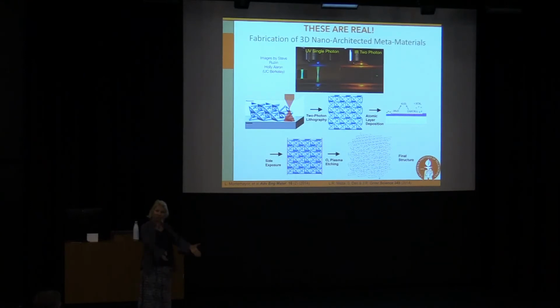So we expose some of the faces of the cube, and then that allows the oxygen plasma to access the tubes and the material inside. And so we etch out this scaffold that was so painstakingly written. So what we end up with is a replica, the hollow tube replica of what we had designed, and that's what allows the materials to be so rich.